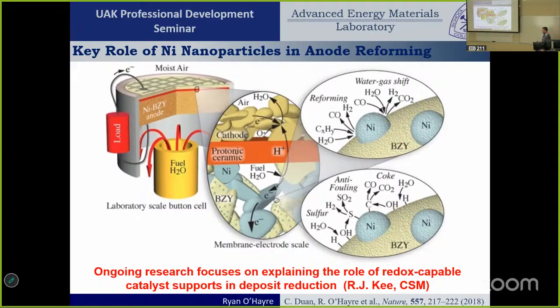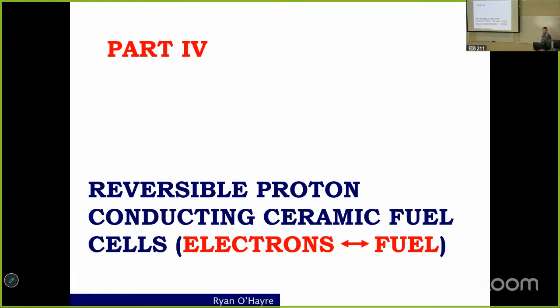So why does this work? Well, this is something we're still exploring. It's all this chemistry stuff, so I'm not going to bore you with the details, but basically there's interesting surface chemistry associated with these ceramics. And you get these hydroxide type species that will eat the carbon, the soot that tries to deposit, and the sulfur, and oxidize it to SO2 or CO or CO2, which will leave. Right, so you basically can clean any solid deposits that start to build up.